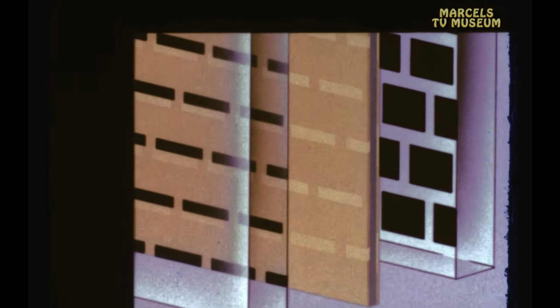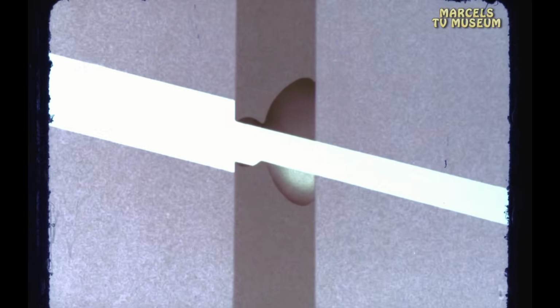Let's look closer at this. The negative pattern of the slots is wider on one side than the other. When the unexposed material under the negative pattern is washed away, we can etch away the iron to give us a hole which is tapered on both sides. This is necessary to avoid reflections from the inside of the holes.